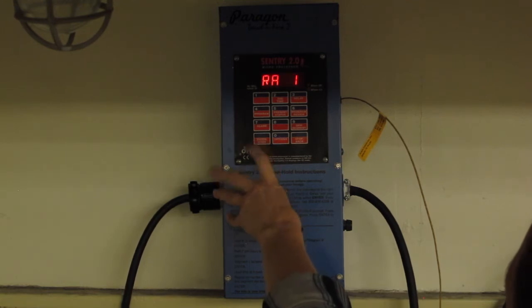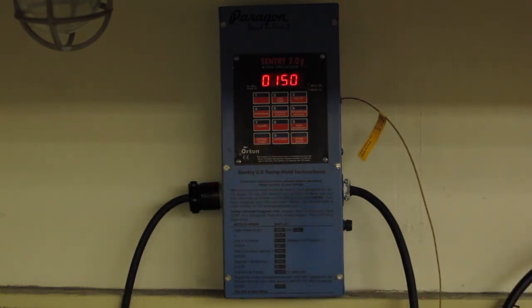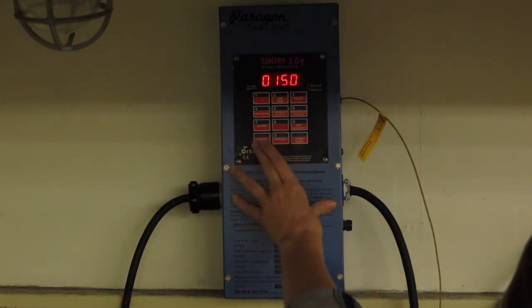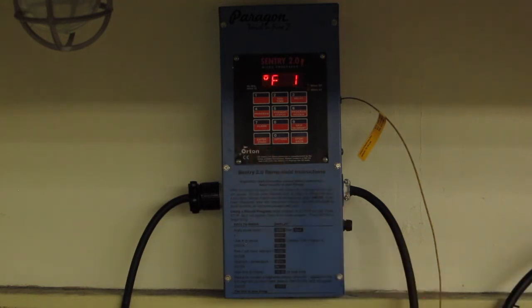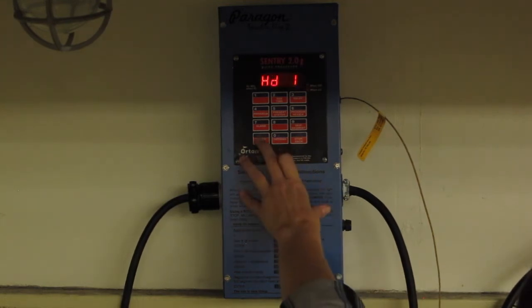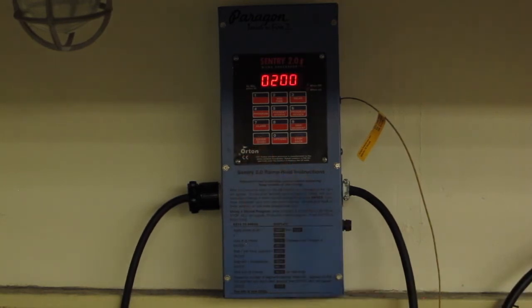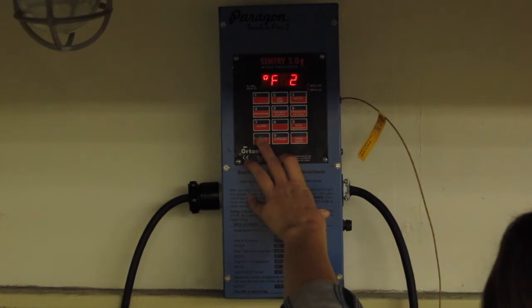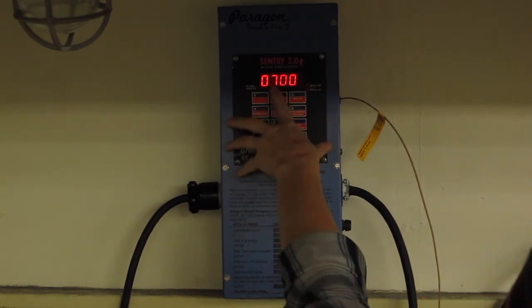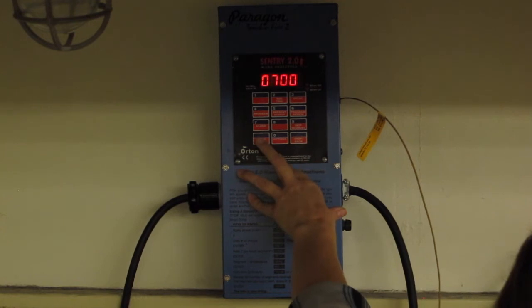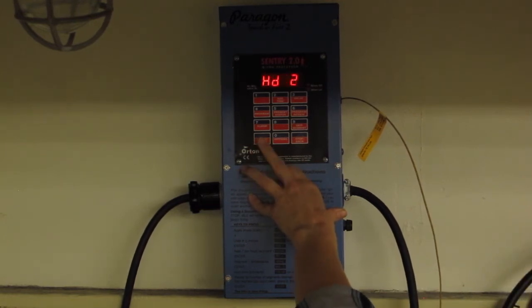The first thing that you're going to see is ramp one is 150, because I need to take two hours to get to 300 degrees. That is telling the computer go 150 at a time until you get to 300 degrees Fahrenheit. It will have a hold time of zero because I don't need it to hold at that temperature for any longer. My ramp two is going to be 200 degrees because I was already at 300 and now I need to slowly ramp up to 700. There's my 700 degrees, and you can see that it has a Fahrenheit temperature so we know we're at the right setting. Again it doesn't need to hold at all so it's going to say zero there.